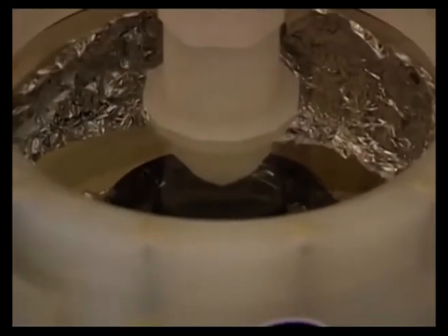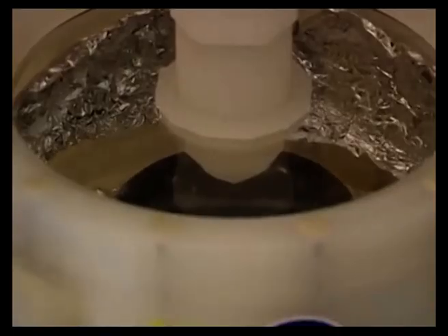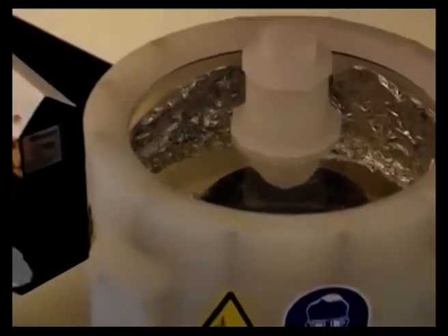Basically close this and just start the spin coating process, and let the film that we have set spread over the whole surface and create a thin film of about 20 to 25 microns of this resist on the surface of the wafer.